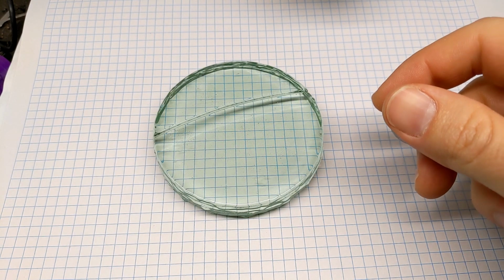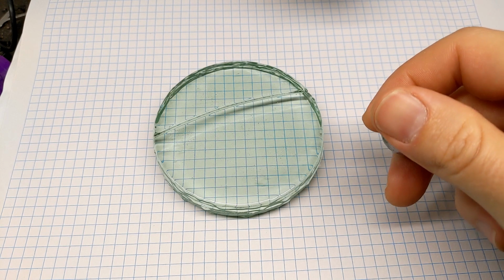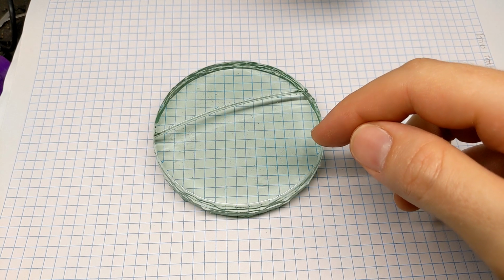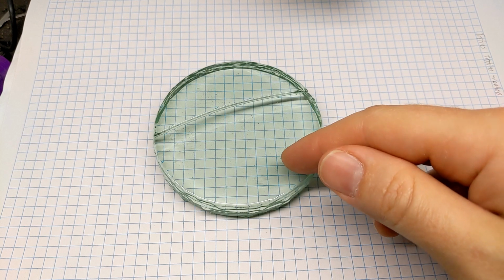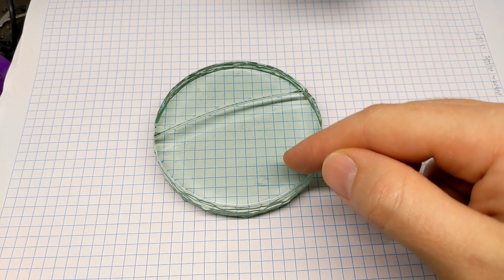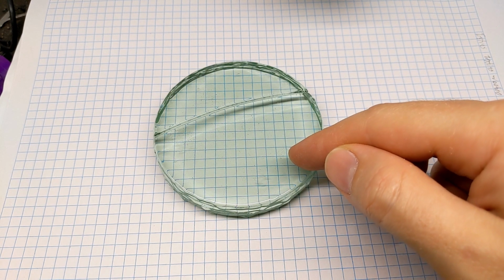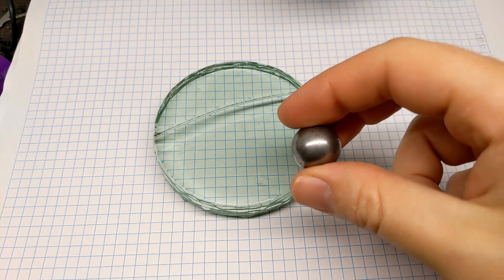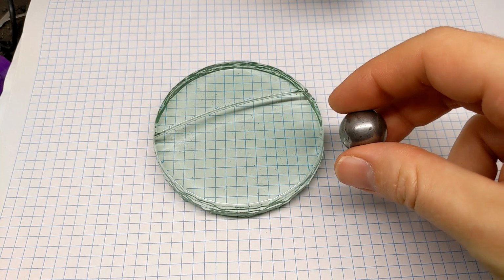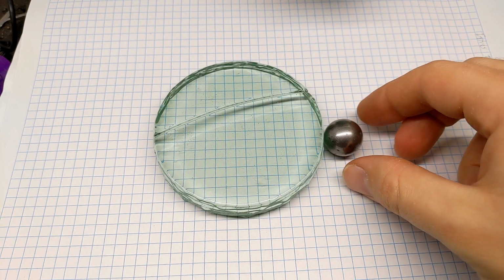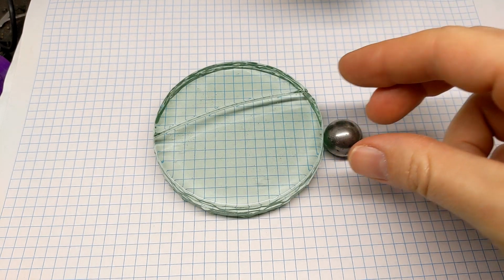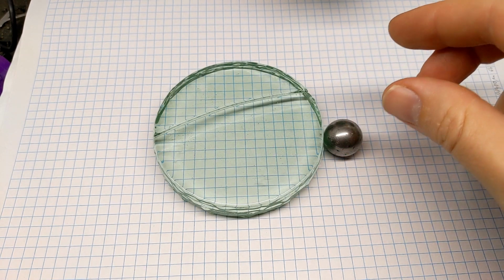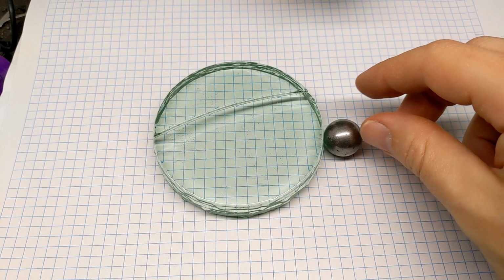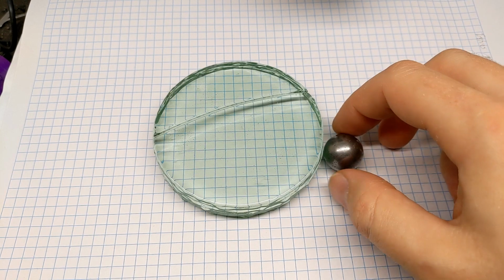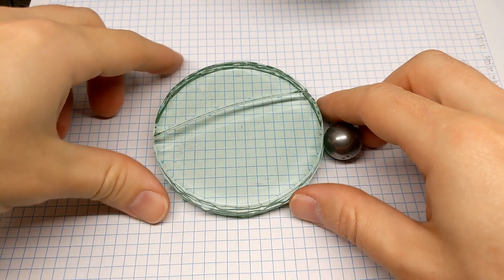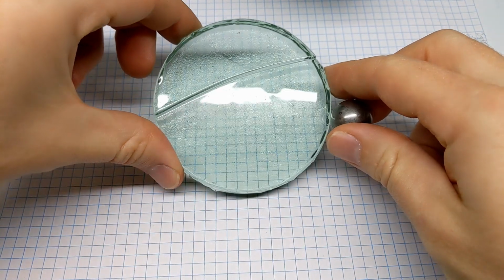other one. I had a look up, read some papers, and apparently for commercial potassium hardening they leave it in there for 30 hours, and reports vary, but anywhere up to 450 degrees. One of them says 300 degrees, but potassium nitrate doesn't melt until 325 or so, so I can discount that one. But yeah, so I'll remelt this one to fix up that little bleb.